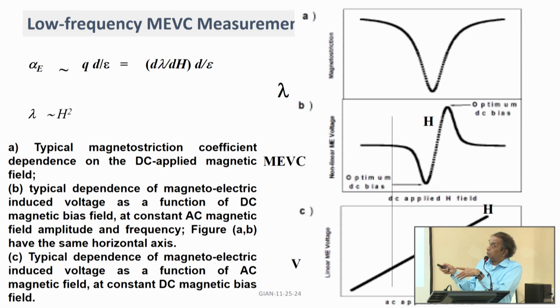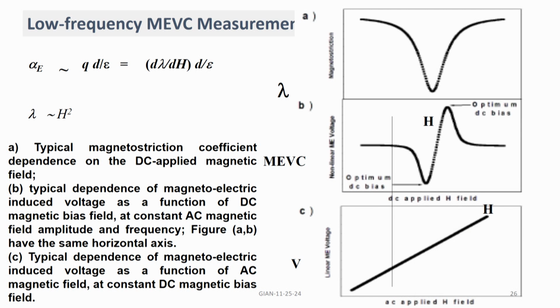Now, when you make the measurement, the voltage coefficient is proportional to the product of Q and d over epsilon. Q is the derivative d lambda dh. What's shown here on the right is lambda versus h. D lambda dh is the first derivative of this, and this is what is shown in the middle one.